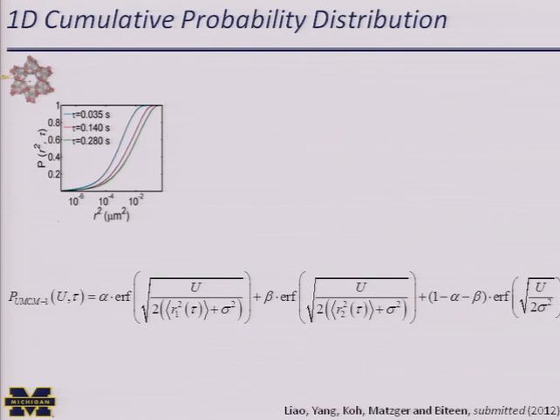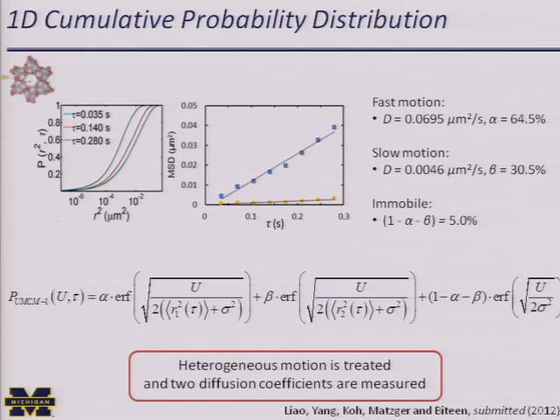So we fit for different taus. Here's a representative short tau, medium tau, and long tau. We could fit these CPD functions and get alpha, beta, and R squared 1 and R squared 2, the MSDs. And we plot MSD as a function of tau. So here for the fast motion, we get a diffusion coefficient. For slow motion, we get a diffusion coefficient that's about an order of magnitude slower. So these are both linear. Neither are immobile. One is moving quickly and one is moving slowly. And then 5% of the molecules are left over as immobile, which agrees with the qualitative data.